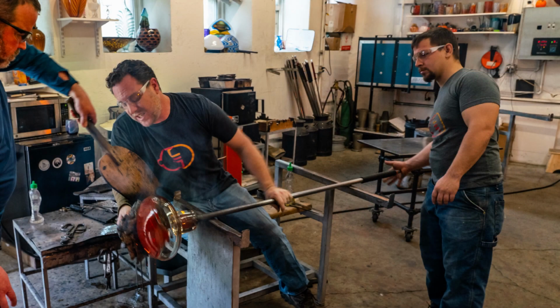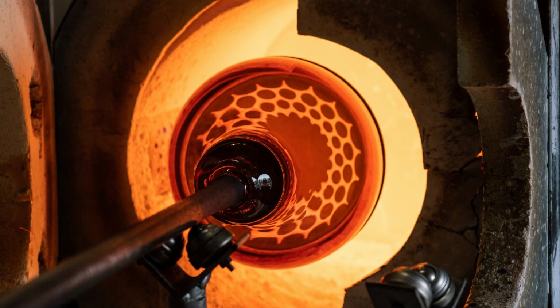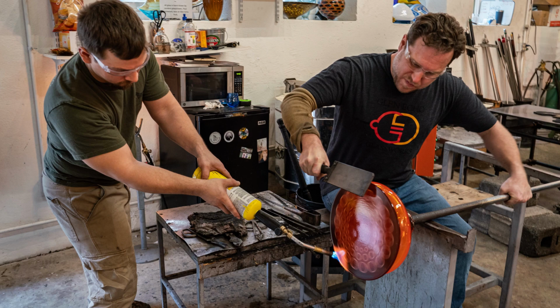A lot of times we cap the end of the pipe to hold that air pressure in so that we can push against the outside of the bubble. That plate inherently is not going to heat evenly. So as we go into the furnace to balance out the heat, we're constantly pushing the outside lip of the plate back in while the center is able to build up heat, and we can cap the pressure in there to keep forcing a direction to where the piece is going to go instead of collapsing from all the pressure we have to push on it. There's a lot of balance there.